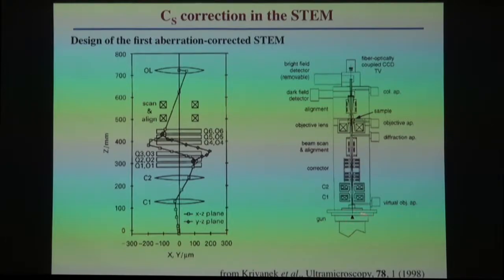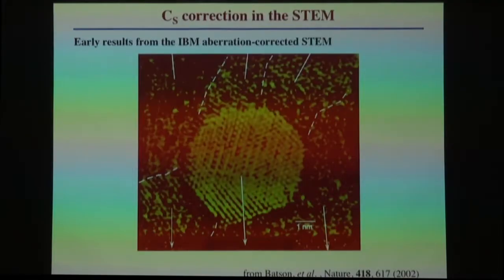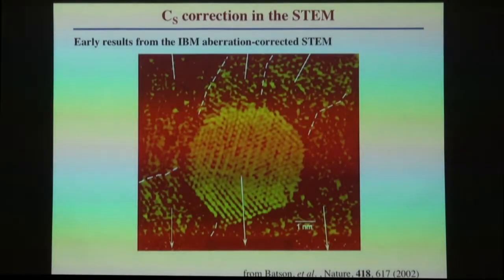So you put it in, there's the gun, condenser lenses, there is the corrector, and very striking images were published by Batson. I just took this from his paper in Nature. These little yellow spots here correspond to gold atoms that are running around on the surface of the substrate while they look at the sample. And so this is a little raft of gold, and early results from aberration-corrected STEM.